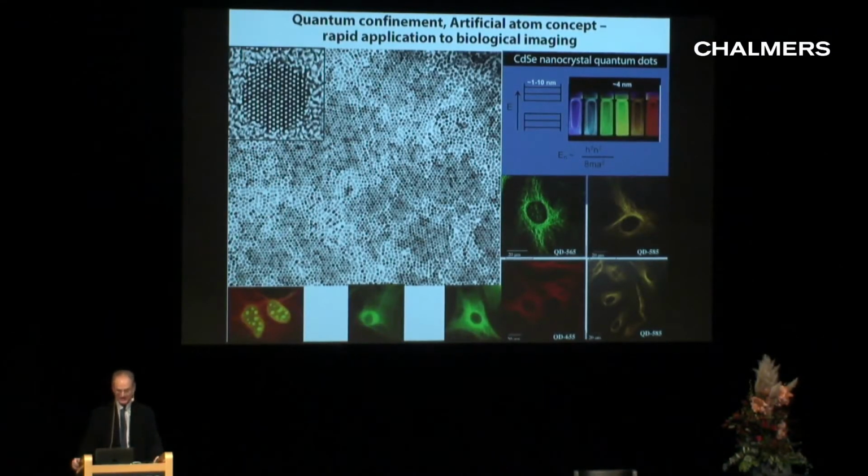Richard mentioned to you this notion that if we have an inorganic semiconductor, typically two charges, an electron and a hole, just like an electron and a proton, say, in vacuum, they're going to feel each other and bind very strongly, the Coulomb attraction. But if it's in a medium that has a very, very high dielectric constant, that means it's a medium where the electric field isn't as felt as strongly by each other. That weakens their interaction. So that's true of these inorganic materials. They have a weak Coulomb interaction because the atoms they're made out of are so polarizable, the electric field doesn't connect them very strongly.